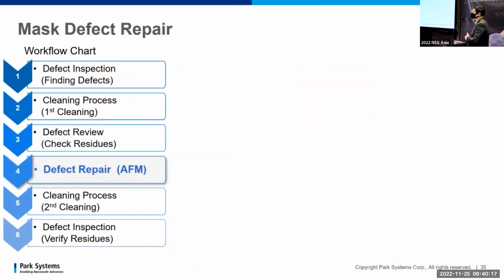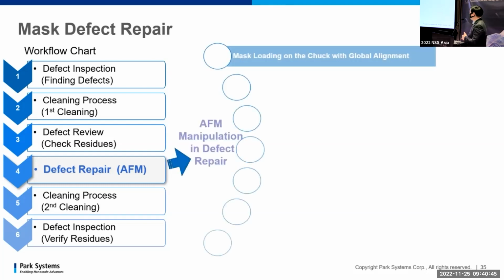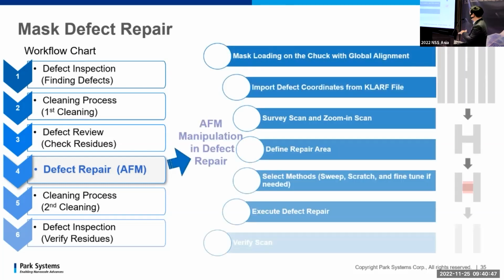And lastly, there's another interesting application of SPM. I told you that in the EUV process, defect control is so important. So people try to use mask defect repair. Usually they use a wet process to remove the defect, but when a defect becomes 30 or 50 nanometers, it sticks to the surface so hard that the wet process cannot remove it. That's why AFM is utilized in this process to remove the defect.